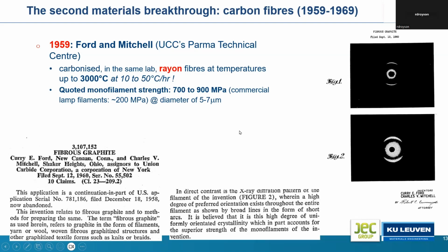The interesting thing, however, in this research is that, as far as I could reconstruct, for the first time there was made a link between the orientation of the graphitic layers in the carbon fibers on one hand and the mechanical properties on the other hand.